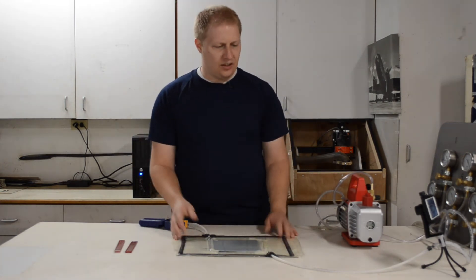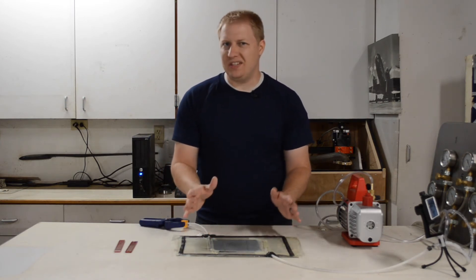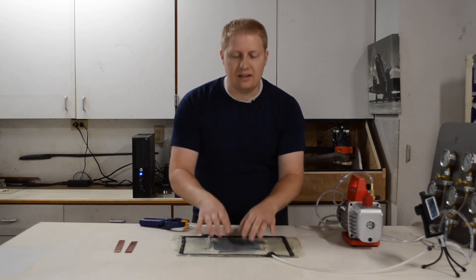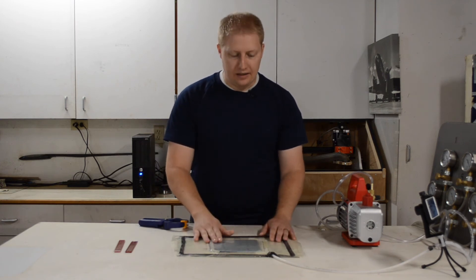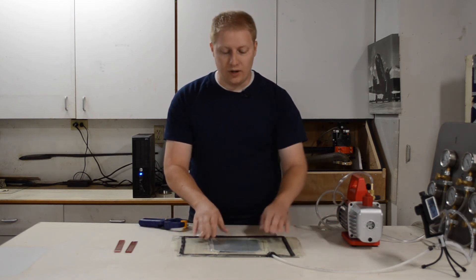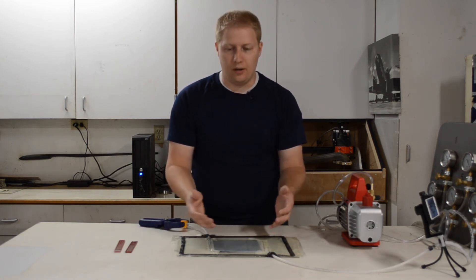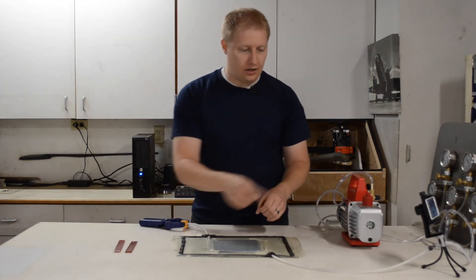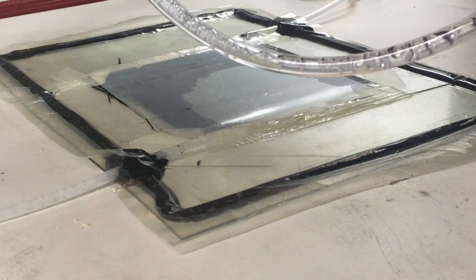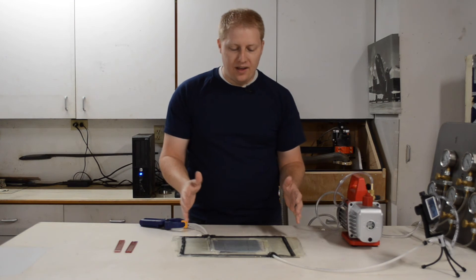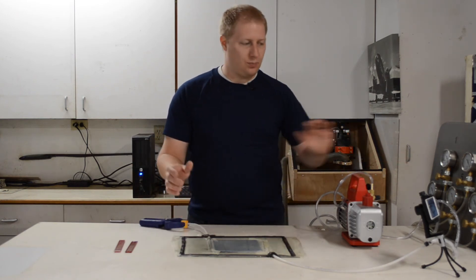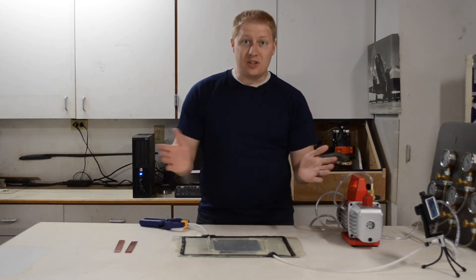And then the last thing I think is worth mentioning is that it sucked the resin in, and you can actually see that this whole area right here had bubbled up a little bit with some extra resin. There was more resin in the layup than there needed to be. Now as soon as I kinked the hose and clamped it and stopped sucking resin in, then it just pulled all that out and it was just fine. It infused the rest of it and sucked the excess out through the tube, and so we have a net layup that's the right thickness, or it should be. We'll measure it with the calipers when we get there. But it ended up sucking a lot of resin out. In fact, in this tube, there's a whole bunch of resin just all up in there. Maybe used about 12 inches of the tube that I had not expected to use. Not a big deal. I would rather have that happen than have bare spots, dry spots in my layup. So I'd rather have a little extra and spend 10 cents on some extra tubing to just replace the stuff that got filled up with epoxy when we're done. Not a big deal. But let's go ahead and get this thing open and see how it turned out.